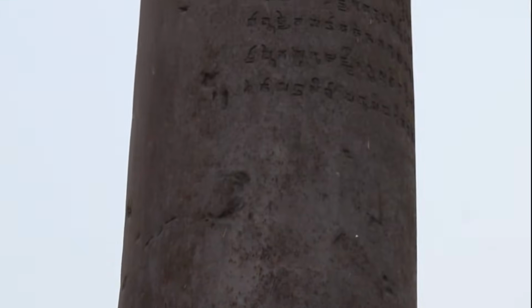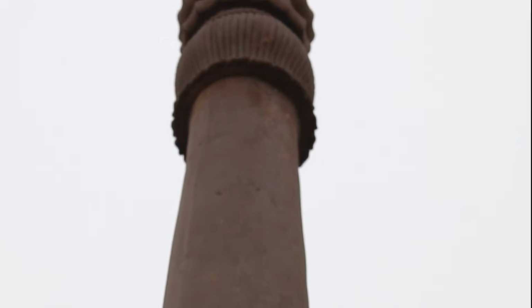As it slowly oxidized over centuries, a thin layer of crystalline iron hydrogen phosphate hydrate formed at the metal oxide interface. This layer is incredibly stable and non-porous, functioning like ceramic coating. Moisture cannot penetrate it. The pillar essentially stopped rusting after forming this protective skin.